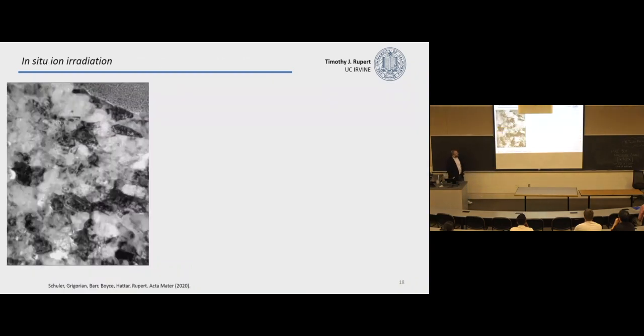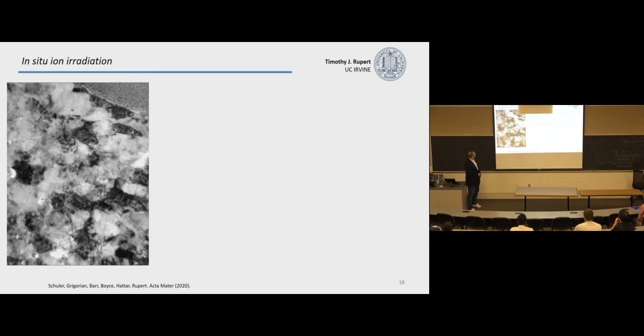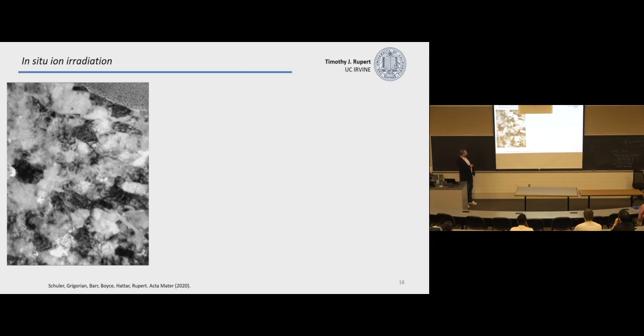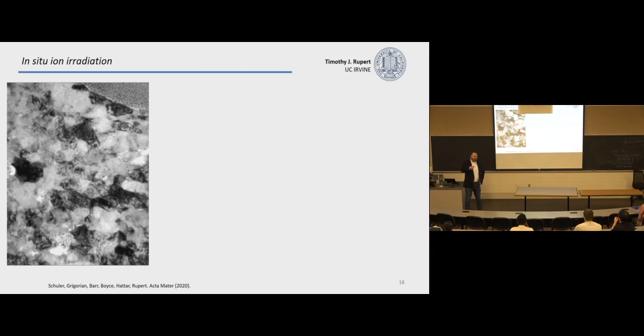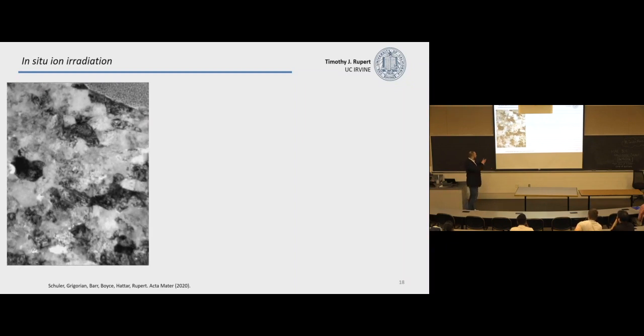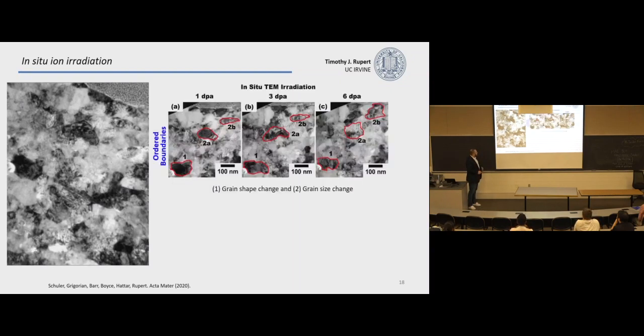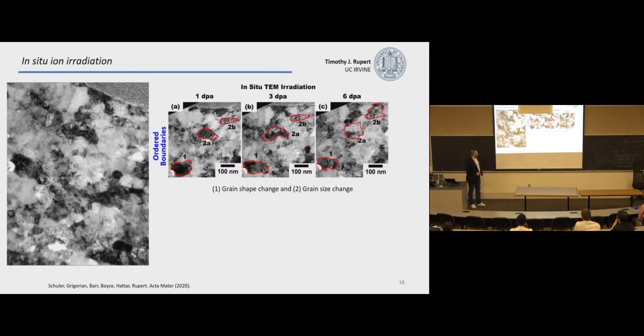So we can take this same nanocrystalline copper zirconium and bombard your material with energetic ions. When you're seeing changes in the contrast, it's not necessarily that you're seeing the charged ion, you're seeing the effect of that charged ion. So it creates defects. Sometimes these coalesce into dislocation loops and things like that. To first order, you can go and look at how stable your microstructure is against this irradiation.